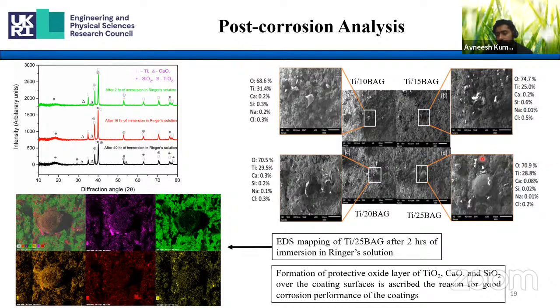We also mapped this titanium 25% coating, and we found that there was some sodium, calcium, oxygen, silicon, and titanium that we were able to detect. Then, to confirm whether there was formation of oxide layers which protected the substrate surface, we did some XRD analysis. In the XRD we found that there was a calcium oxide layer, silicon oxide, and titanium oxide, which helped to protect the substrate from corrosion. Actually, they worked as a barrier to electrolyte penetrating through the coatings.